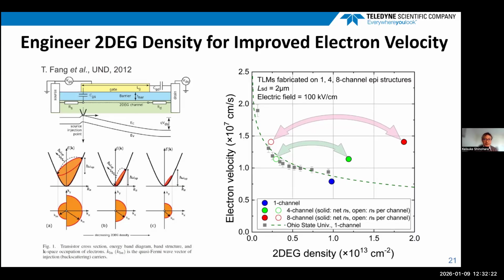So here I show the electron velocity experimentally measured as a function of the 2DEG density. In the multi-channel structure, we can achieve high electron velocity even for high 2DEG density by reducing the 2DEG density per channel, which effectively improves the high frequency performance of the transistors.